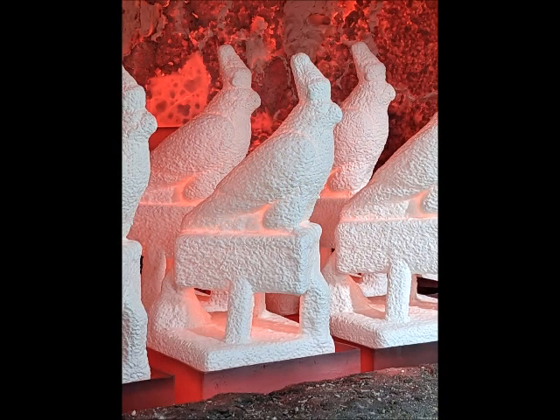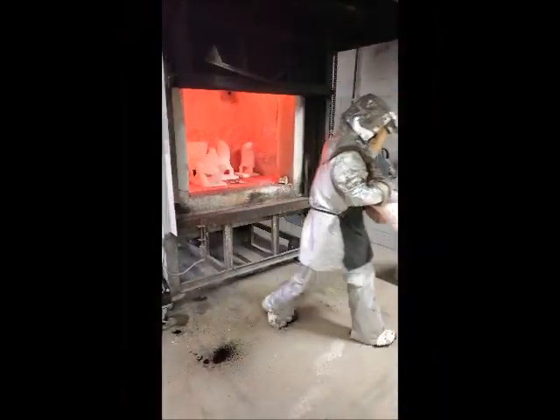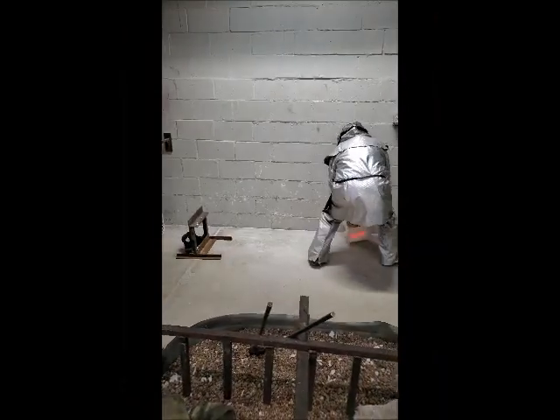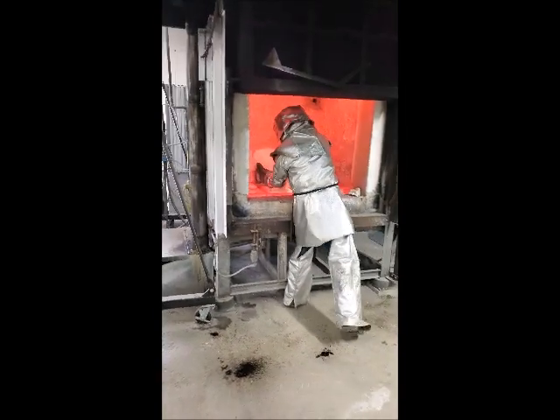Kiln firing also vitrifies the silica shell, meaning when the silica shell is heated to this temperature, the heating process hardens the silica and converts it into a hard ceramic shell. The hardened ceramic shell is then able to withstand the molten bronze when it is poured into the ceramic shell. The ceramic shell is then removed from the kiln and is allowed to cool and is inspected for any cracks or imperfections which must be repaired.